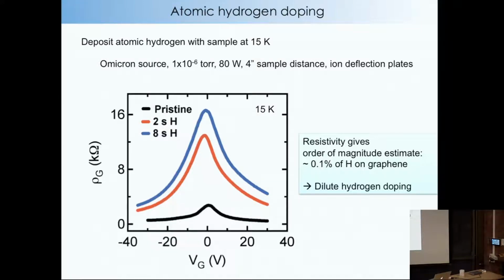This is for the clean graphene. And when you put on hydrogen, this is for 2 seconds worth, this is for 8 seconds worth. I don't know what the coverage is, but based on the change in resistance, we estimate that it's a fraction of a percent. And what you can see is that the resistance goes much higher. What's happening is this localization of electrons that was mentioned earlier, right? And so there's some resonant scattering happening from the hydrogen-induced defect.